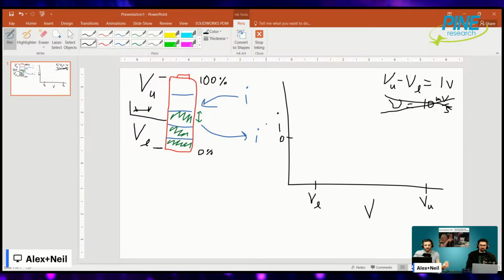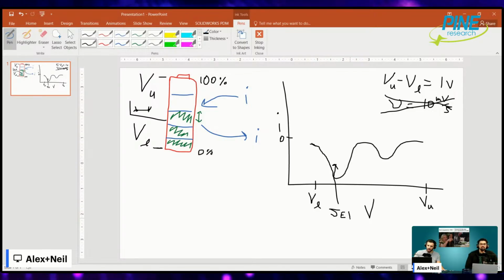The other reason that's built into this is that as you do your CV, for instance, let's say you go from VU to VL, you scan negatively. You might get a peak depending on how fast you scan, all this kind of stuff. Usually, like in the first scan, you'll get a big negative peak, and something like this indicates the SEI formation. So if you did that really fast, again, without taking some of this into account, you might be forming the SEI in a very bad way. Like it might not form properly. And so it could be unstable. If the SEI collapses, you could have a catastrophic failure of your battery. Things like that are prone to happening.